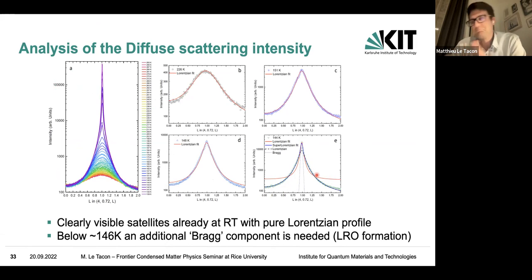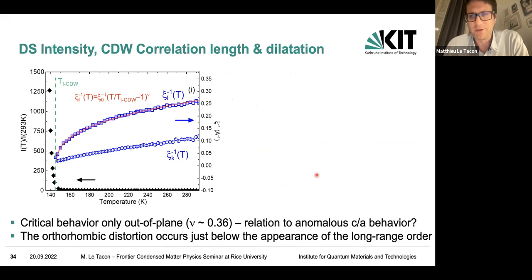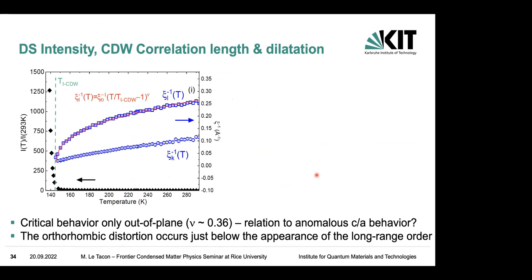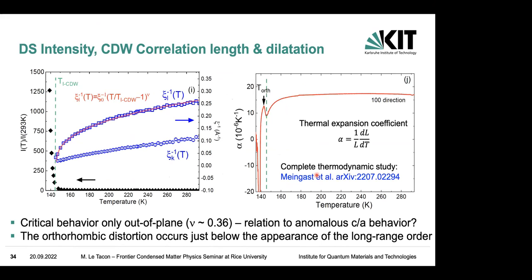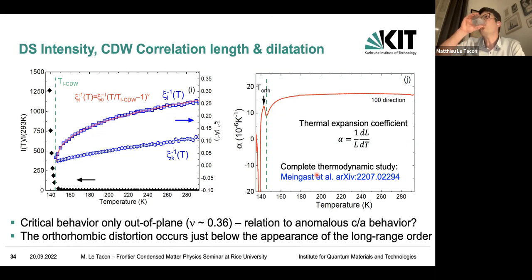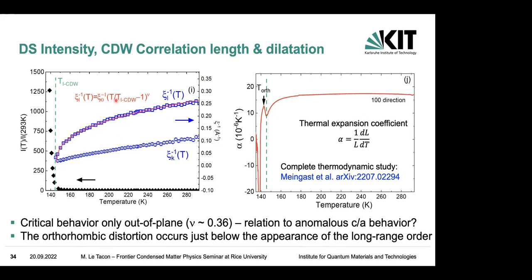Well, I don't know. To me, it looks like it's diverging, but we can discuss. But there's no Curie-Weiss-like tail, right? It seems like it goes to 140-some Kelvin, then it directly happens. Not like your standard second-order phase transition. You'd expect a long Curie-Weiss or whatever fluctuation regime. I mean, this looks pretty much like, that's K to the minus 1, right? It just follows this functional form. So it looks pretty much Curie-Weiss to me, right?